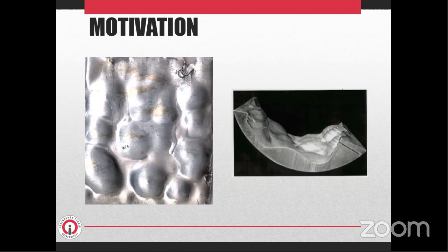The undulatory structures are shown clearly in the pictures. The picture on the left side shows these variations on the solidified shell thickness after interrupting the solidification process of aluminum on the planar mold. The picture on the right-hand side shows a similar undulatory structure when aluminum solidifies in the cylindrical mold. Such uneven undulations are not desirable in manufacturing because the associated thermal distortions in the solidified shell cause several defects in the solidified ingot, such as cracks.